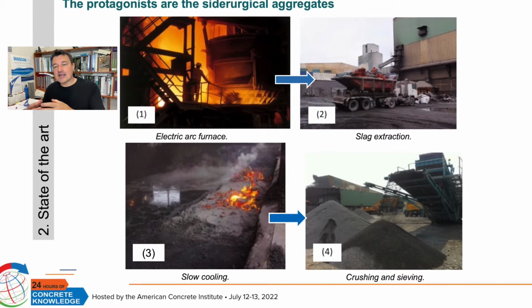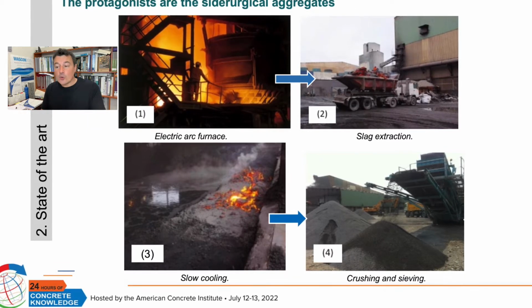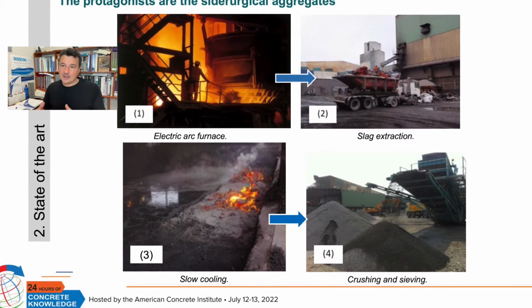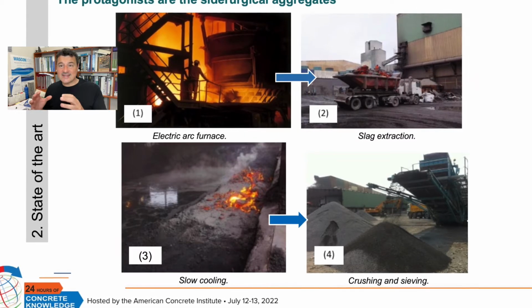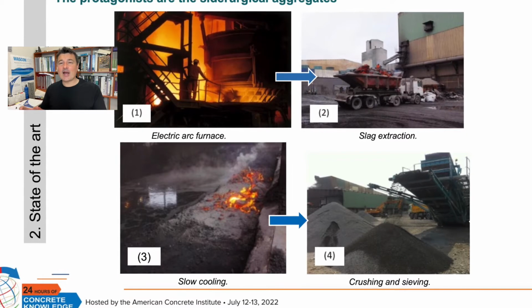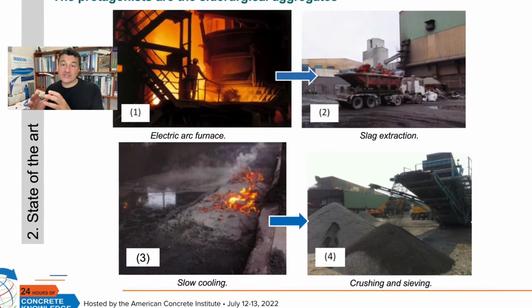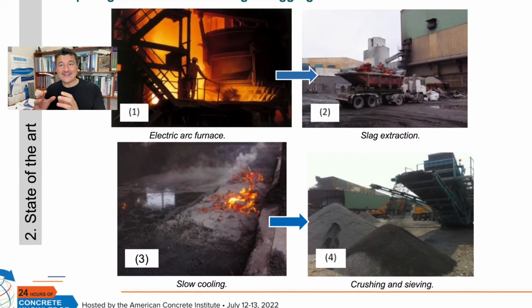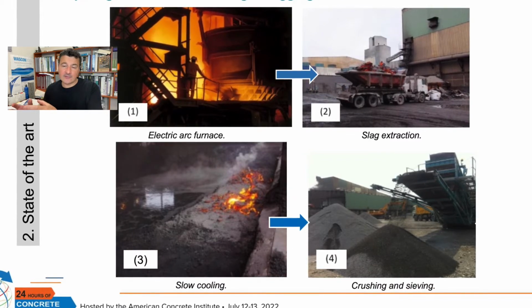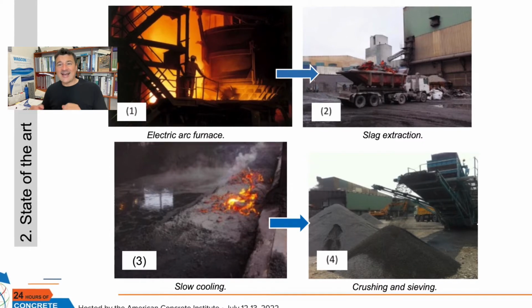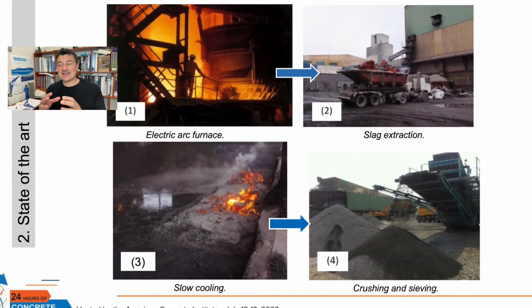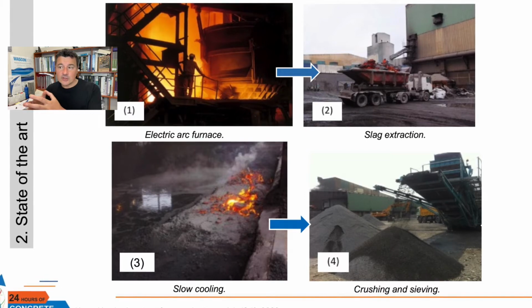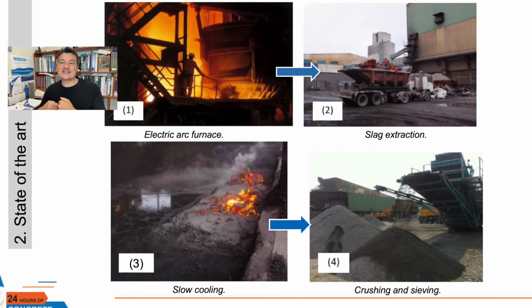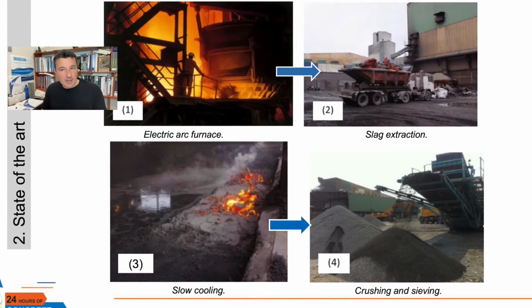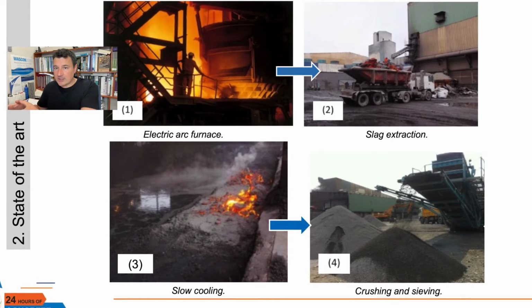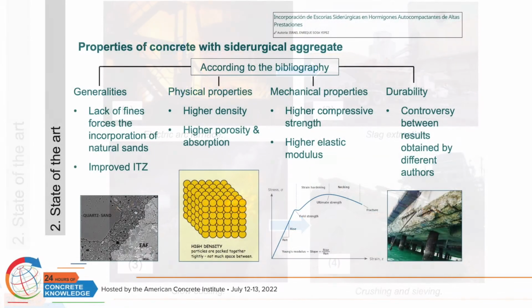After obtaining the slag from the electric arc furnace, we try to cool the slag slowly, because with the slow cooling, we obtain a crystalline structure of this material in order to prevent the reactivity of the material after using it in concrete. After the cooling, sometimes it is necessary to crush the material and sieve in order to obtain the grading that it is necessary to produce the siderurgical aggregate in order to produce concrete with it.